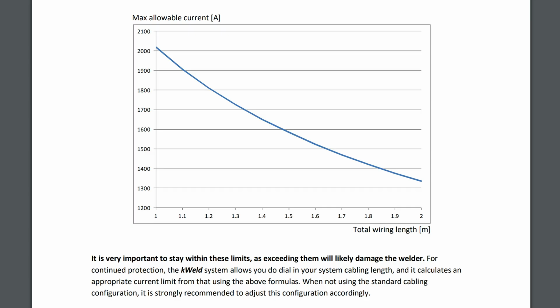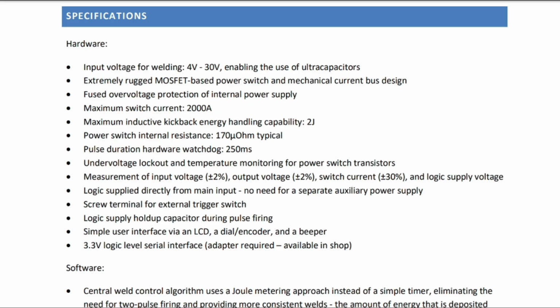Going back to the chart, if we make a vertical line at 1.5 meters of cable length, you can see I'm limited to around 1600 amps of current. Anything more than this and I might damage the k-weld. And with that done, now we need to talk about a power source.